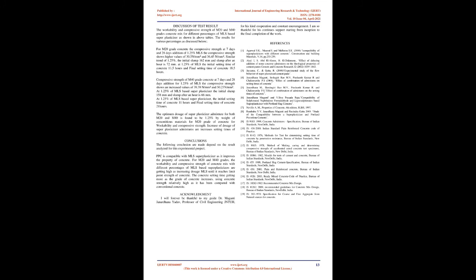Conclusions. The following conclusions are made based on the results analyzed for this experimental project. PPC is compatible with MLS superplasticizer, as it improves the properties of concrete. For M20 and M40 grades, the workability and compressive strength of concrete mixes with different percentages of MLS-based superplasticizer increase with increasing dosage of MLS until reaching a limit point. The concrete setting time increases as the grade of concrete increases. The concrete strength is relatively high compared with conventional concrete.